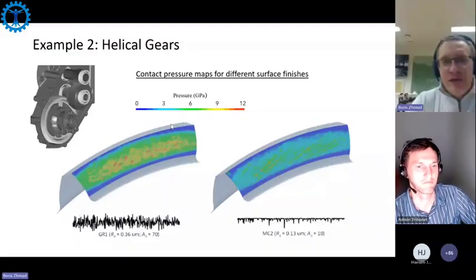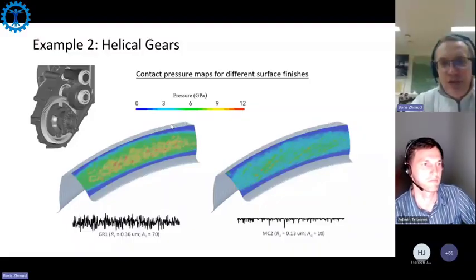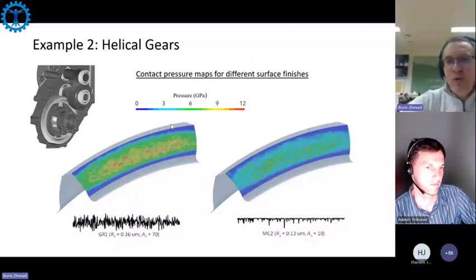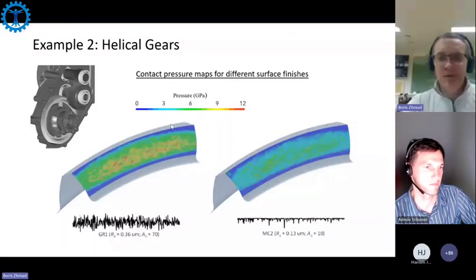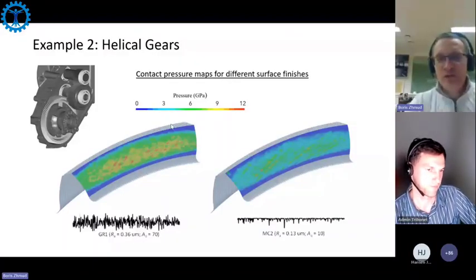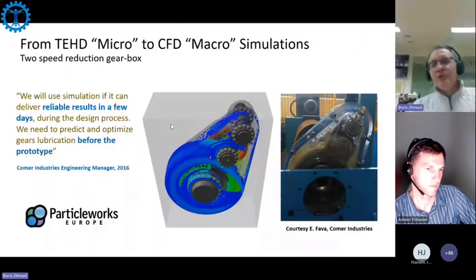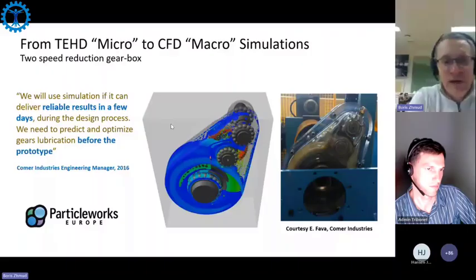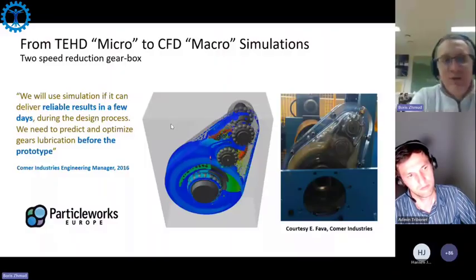We can calculate differences in contact pressure maps for different surface finishes. You will see that with mechano-chemically finished components, you always have a more uniform distribution of stress over the surface, which would minimize pitting damage over the long term and so on. So we also try to get from micro simulation, thermo-elastohydrodynamic simulation, to macro simulation, and this is actually where all the expertise of Particleworks comes in. So I'm extremely happy to be in contact with this company. They have really the world's top expertise in the simulation field.